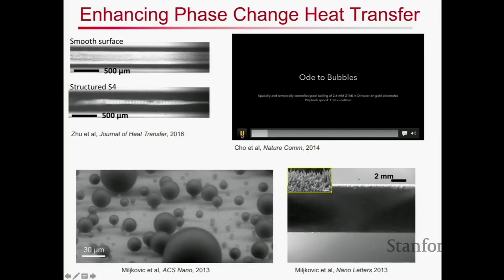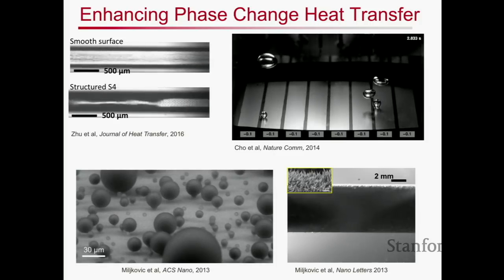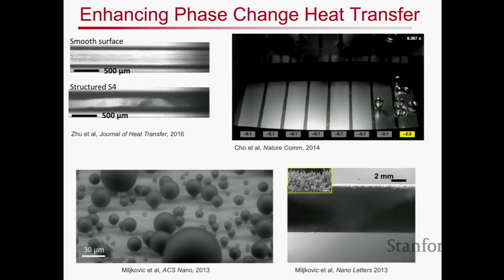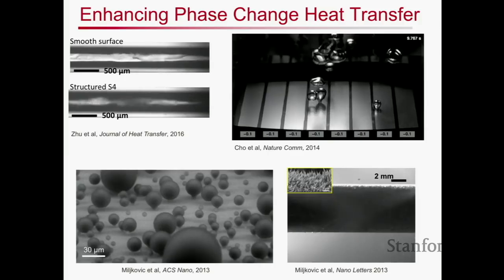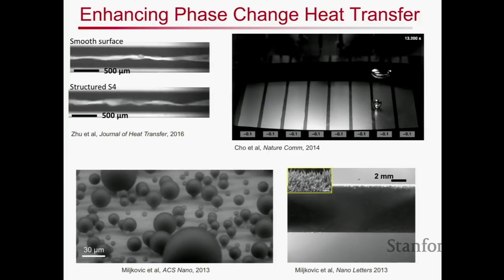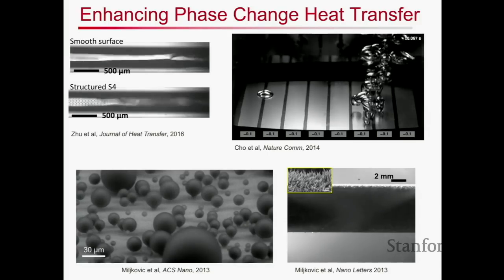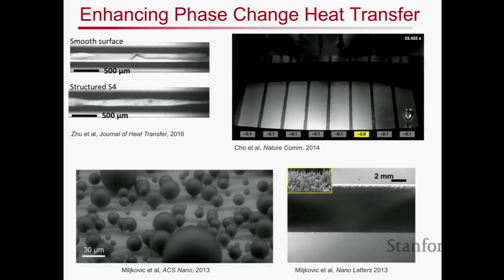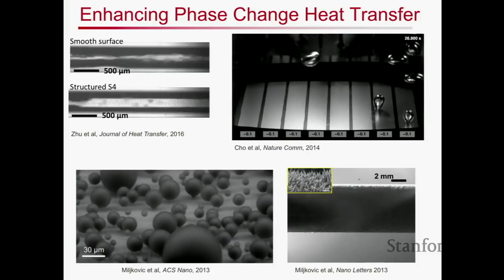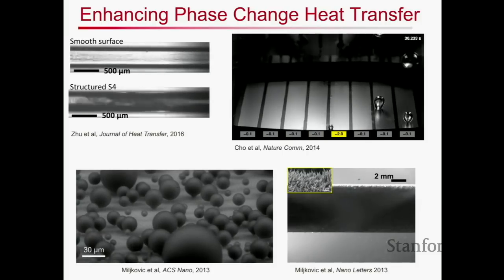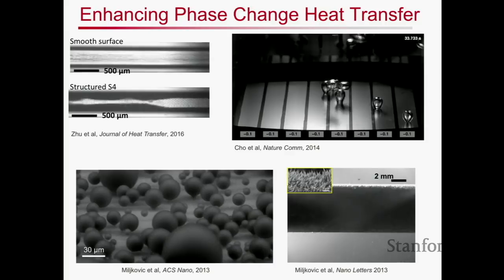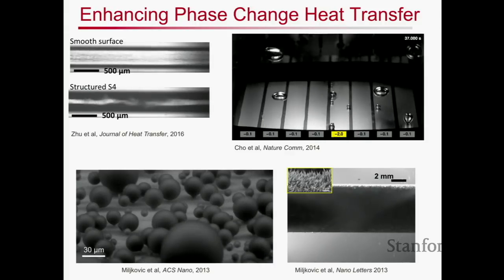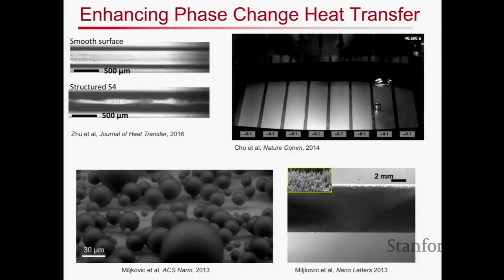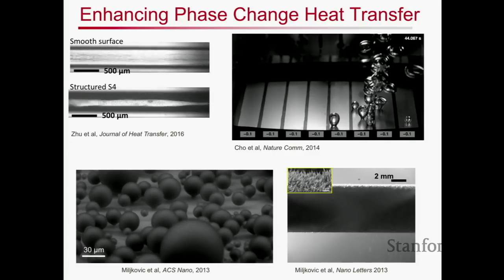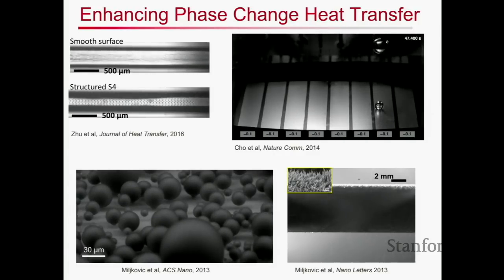We can turn that process on and off by taking advantage of charged surfactants that adsorb onto interfaces, such that when you apply an electric field, you can control locally where that boiling occurs. The idea here is that you're locally changing, at the surface level, the hydrophobicity or the hydrophilicity of the surface. And that can effectively control the nucleation of these bubbles and also the heat transfer coefficient.